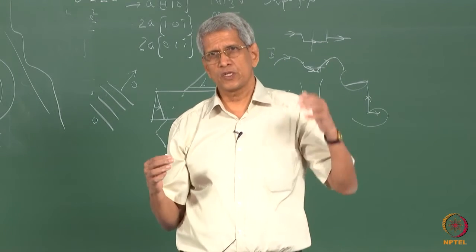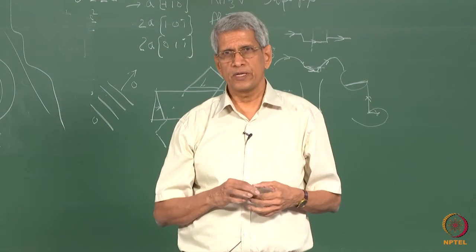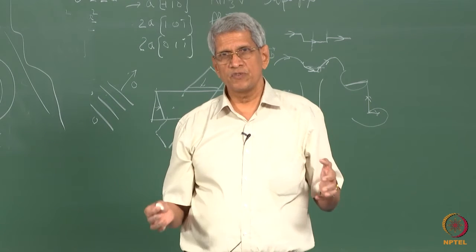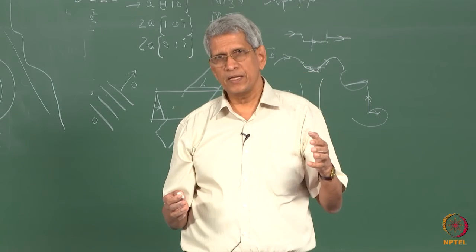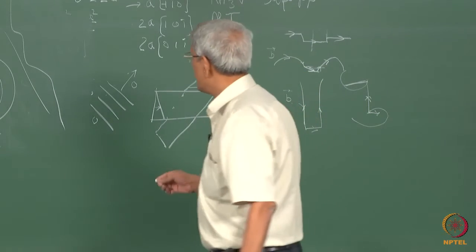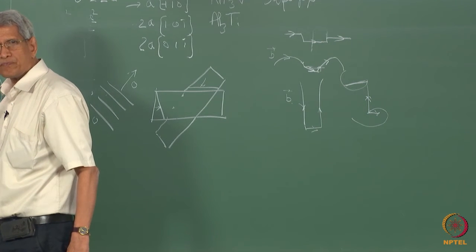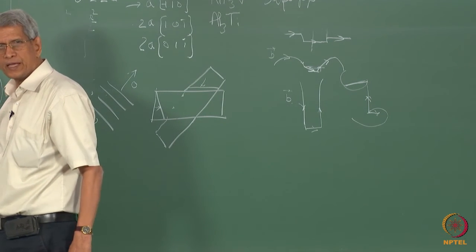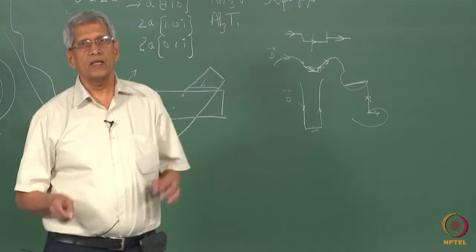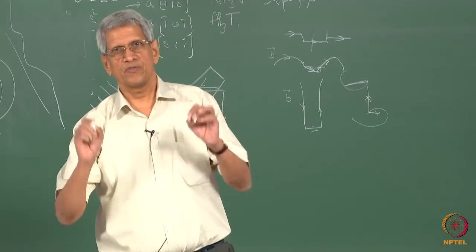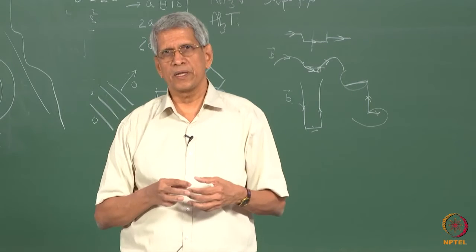When such stresses are acting on the dislocation closer to the boundary, the stress is so high that it can be relieved either by generating some dislocations on the other side, so that they can move, or, if that is not possible, it can create a crack, because once we create a crack at the boundary, then the stress is relieved completely.